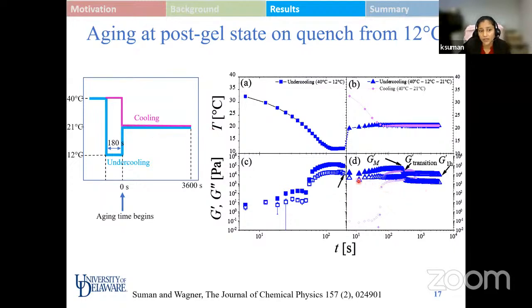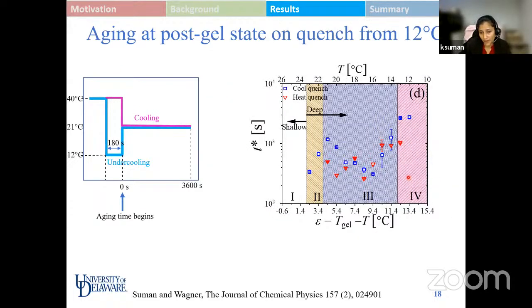On comparing the cooling and the undercooling results in figure D, we can see that both the systems undergo the same transition, which is shown by the drop in modulus value followed by a plateau value. We now compare the transition time during the undercooling protocol and during the cooling protocol. One is achieved while coming from 12 degree to a certain temperature, and the other while coming from 40 degree to a certain temperature. It can be seen that the values are in close proximity, although not identical for both the protocols.